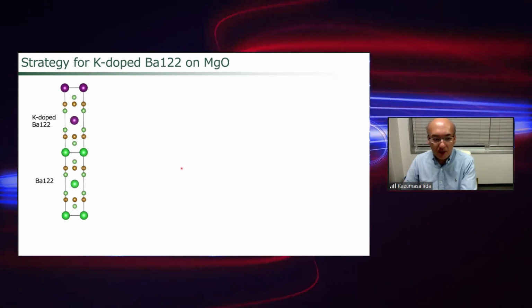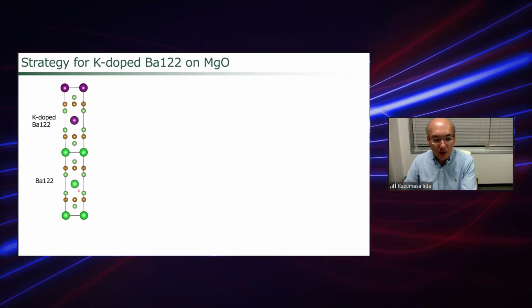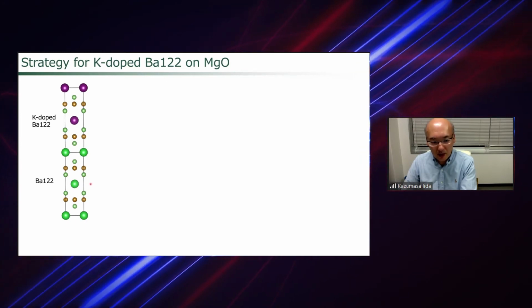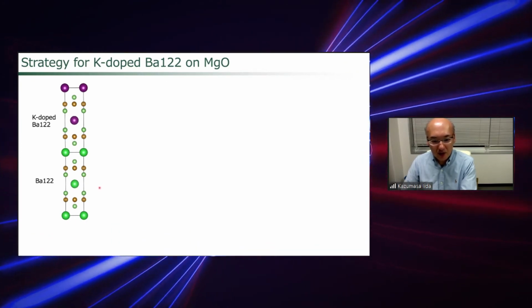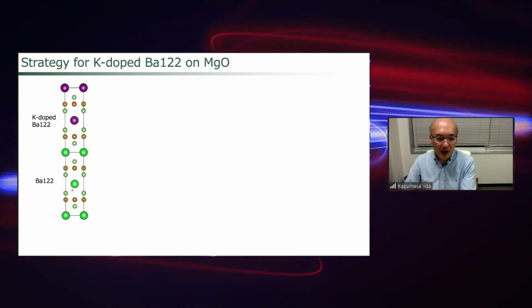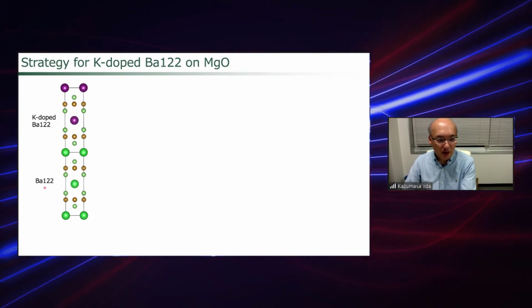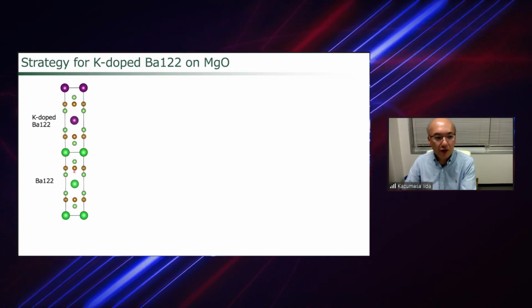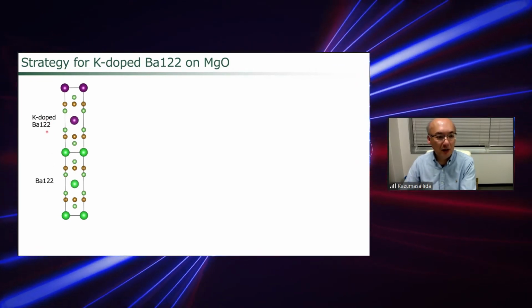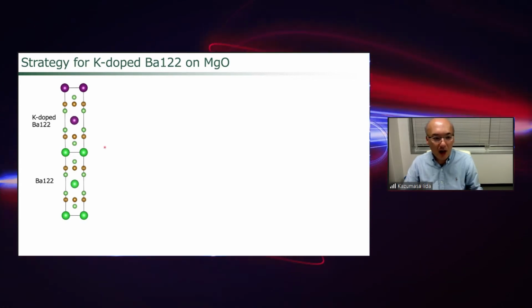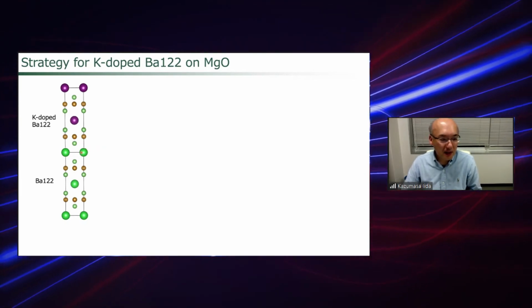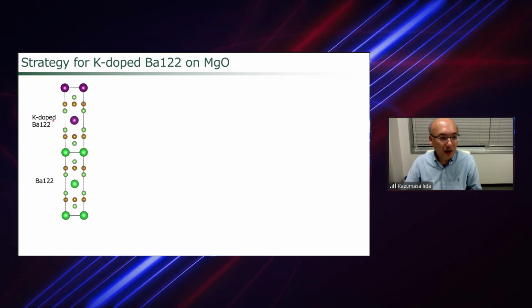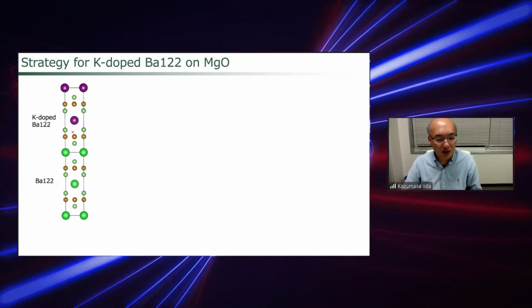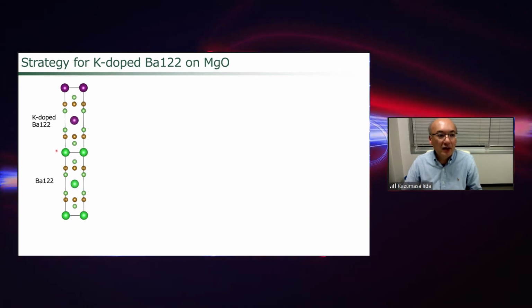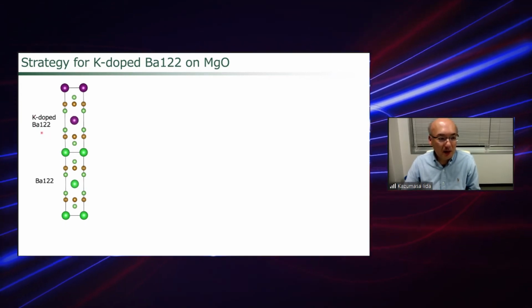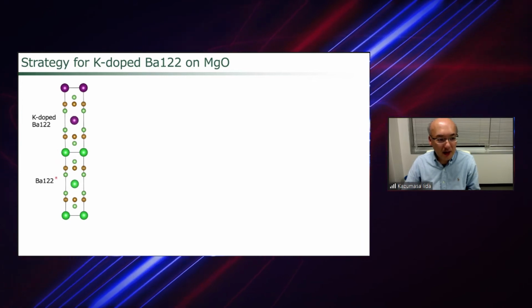But as mentioned before, the barium 122 parent compound can be grown on the magnesium oxide substrate. So that is the reason we consider this barium 122 as a potential buffer layer to grow potassium-doped barium 122, for several reasons. One is that the lattice mismatch between the parent compound and potassium-doped 122 is small. And secondly, the potassium-doped barium 122 is chemically inert against the barium 122.